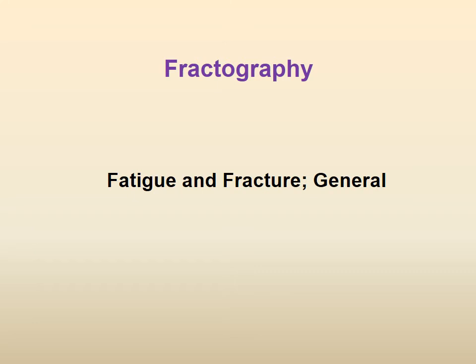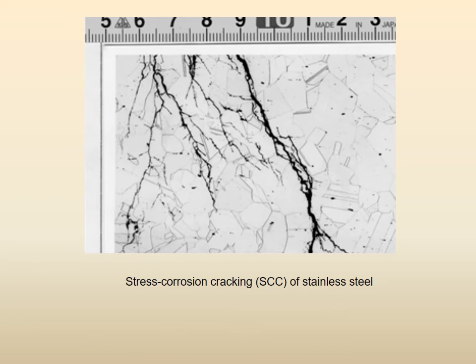So the micrographs that we will be showing you will be of fractured surfaces, and in the beginning we will do general fatigue and fracture. So see here, stress corrosion cracking of a stainless steel. There is corrosion under stress, right? It is not simple corrosion, it is corrosion when at the same time higher loads are applied. So the loads are there, and at the same time there is a corrosive atmosphere. So you see that the cracks are mostly on grain boundaries. So this is stress corrosion cracking.